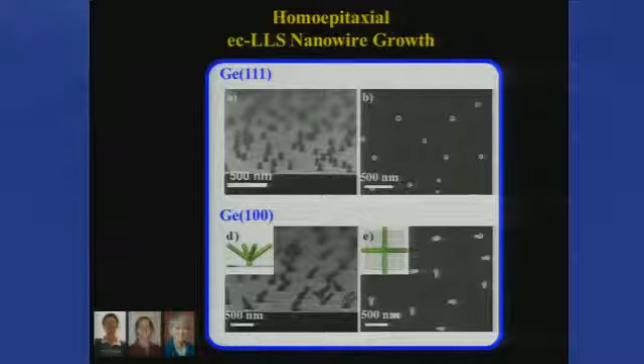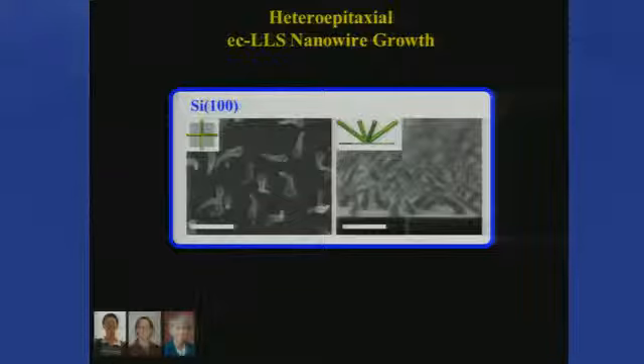These tend to grow in a 111 direction, so on a 111 substrate, they'll grow normal, or straight up. On a 100 substrate, they'll still grow in the 111 direction, but that means they're going to grow off at off angles, as you might predict from just a crystallographic viewpoint. This is growing germanium nanowires on silicon, again showing epitaxy, the ability to grow crystalline materials with some registry with the underlying substrate.